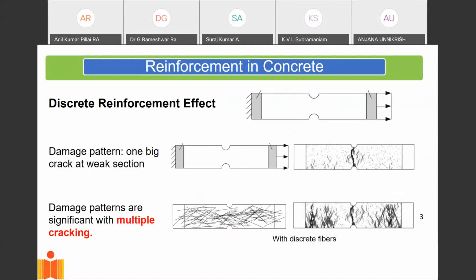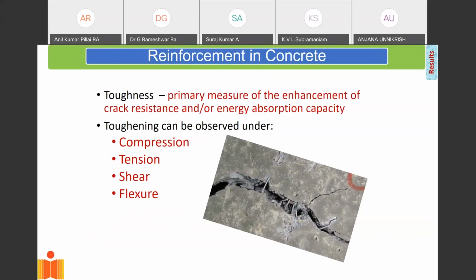And so the whole point of fibers is that if I have fibers, instead of one big crack being formed in reinforced concrete, I'll have 50 small cracks that are formed. Now, the rule when we're trying to deal with cracks is that 50 small cracks, if they're very small, will not allow water to get into concrete. And therefore, it basically also enhances the durability of the material. Whereas if I have one big crack, water can get in and steel will start corroding. So this is the role that these steel fibers play.